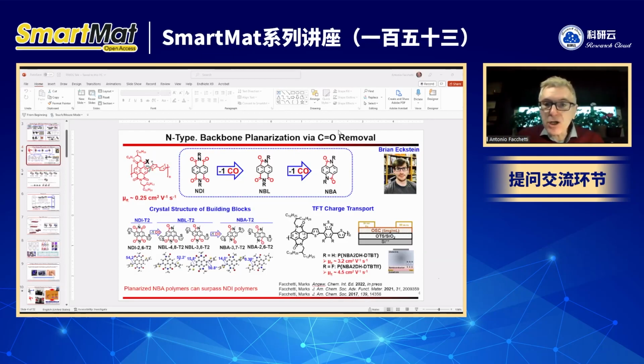And in fact, in order to get good N-type, if you would make this unit with the T2, similar to the N2200, this would be an N-type, but it is not stable in air. You really need to have another electron withdrawing unit to bring the energy back down. I didn't have time to go into the details. So you really have to balance the effect, planarity, but also the energetics.